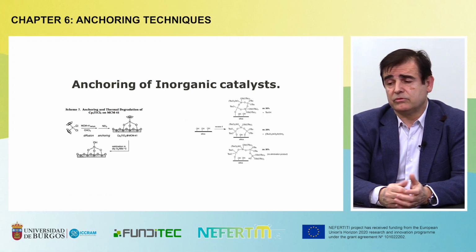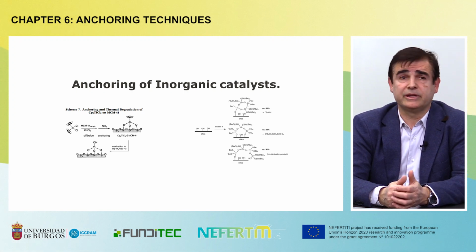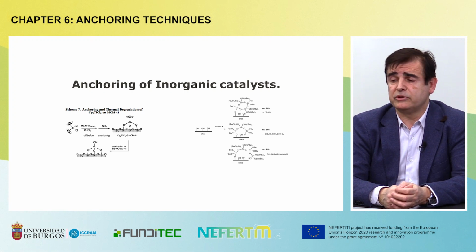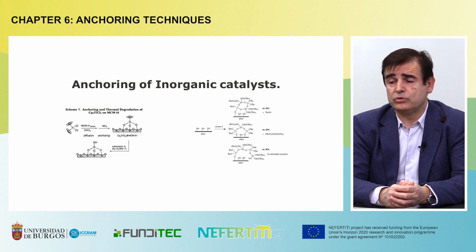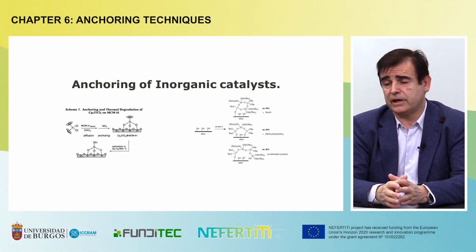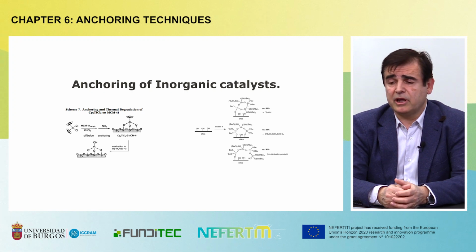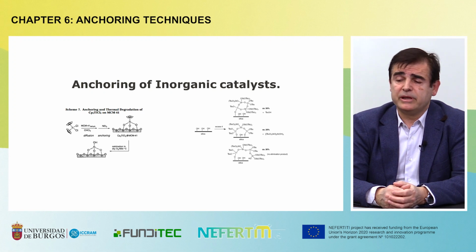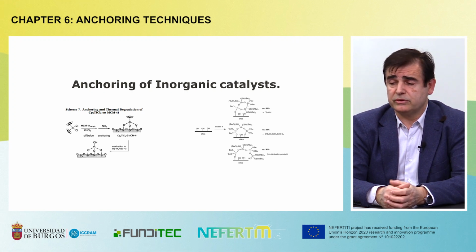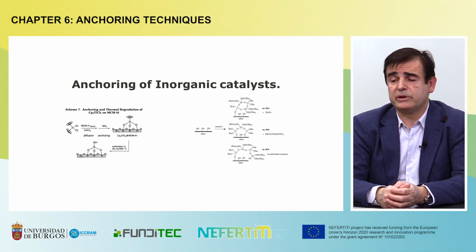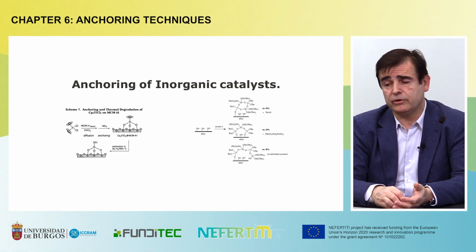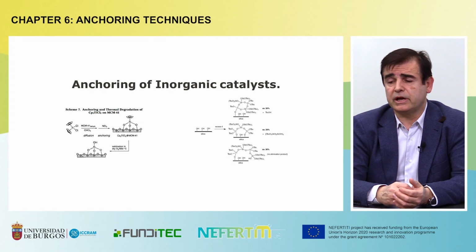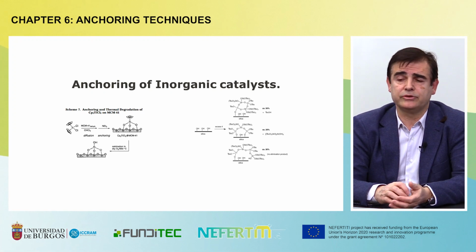One of the strategies consists of anchoring titanium organometallics derivatives. One anchors and calcines, producing a titanium oxide surface modification, to use as a substrate on which to disperse the catalyst. This is the example on the left. The same can be combined with a mixed titanium and silicon complex, the example on the right. By means of a hydrolysis reaction and subsequent condensation, the complex produces the formation of a mixed structure of silicon and titanium, making possible the formation of substrates that can be used for the dispersion of the catalyst of inorganic nature.